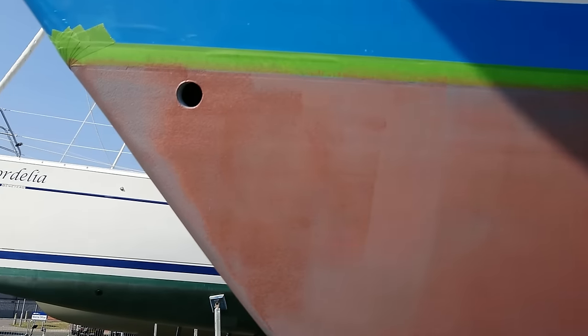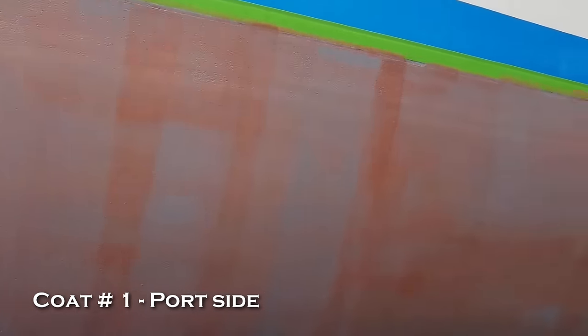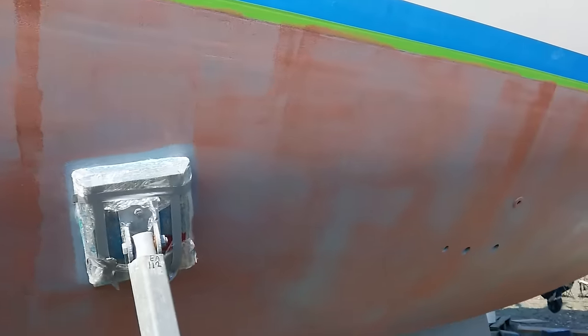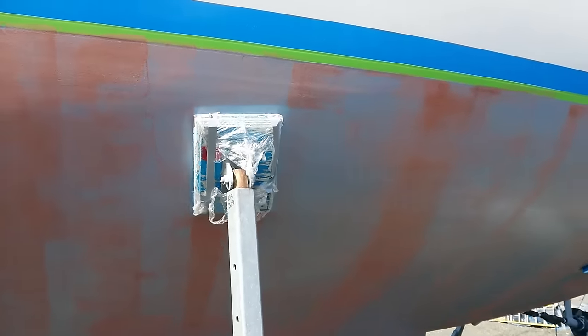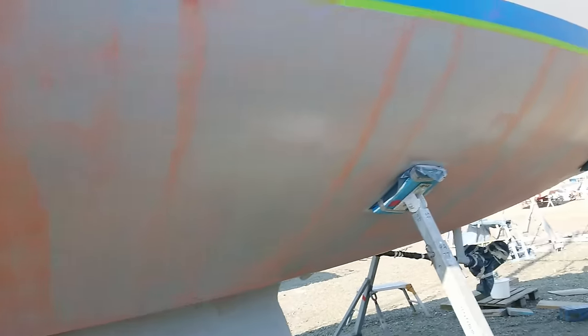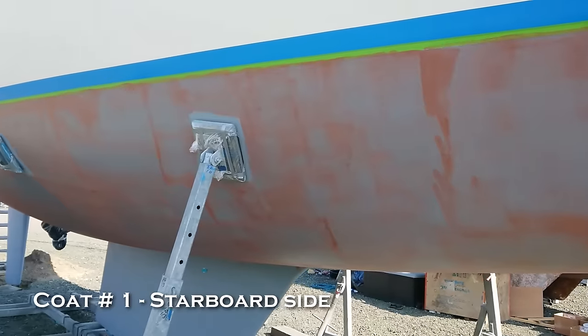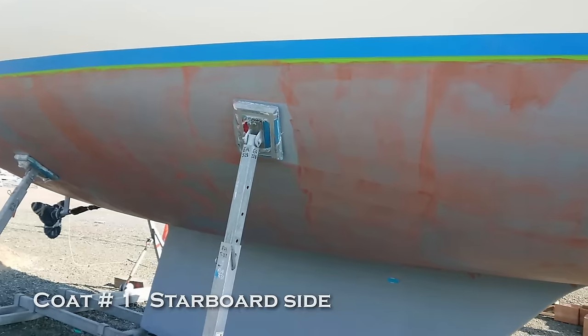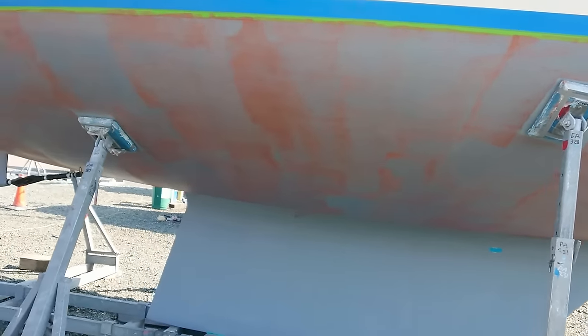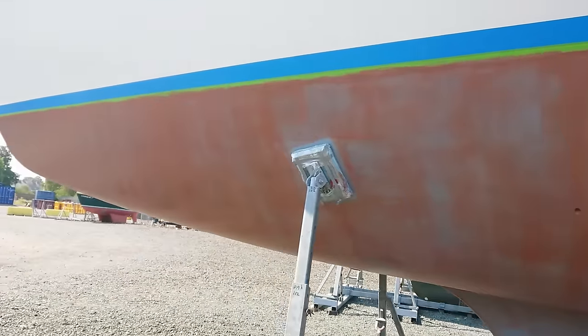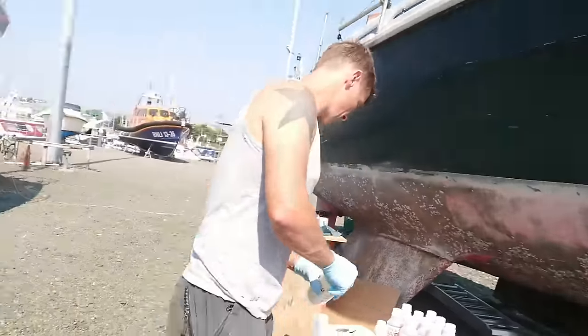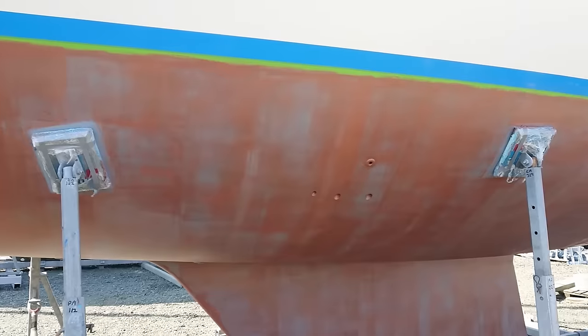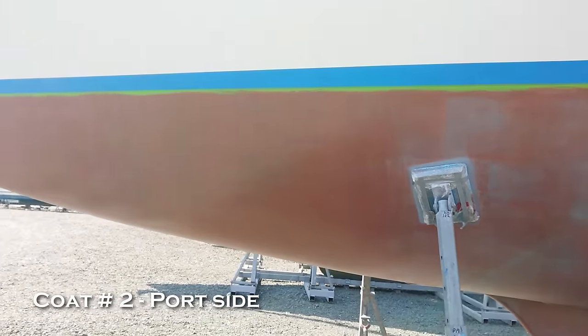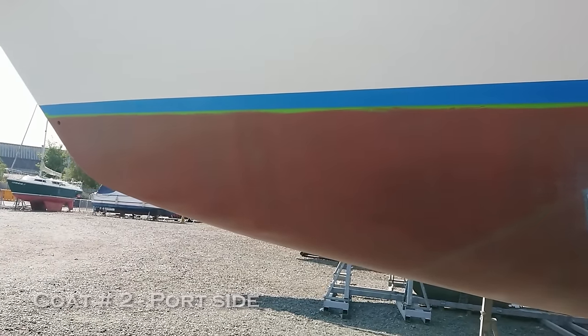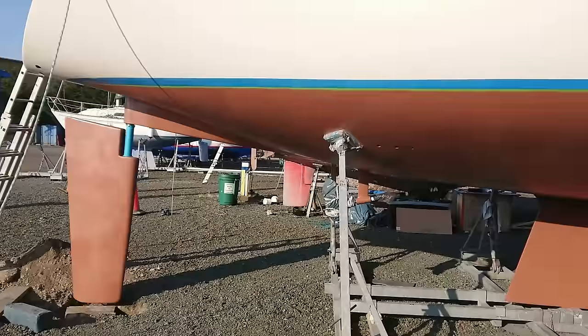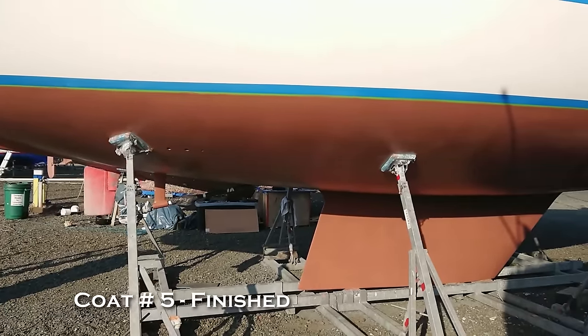We'd watched several videos of it being applied before we started the process, and so we knew that that first layer was going to look very thin and patchy, and as you can see, it most certainly did. As we added each subsequent layer though, it starts to look better and better. It took us both around 6 hours to do the job from start to finish.